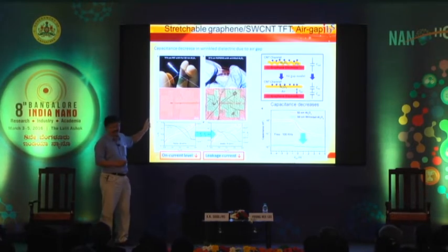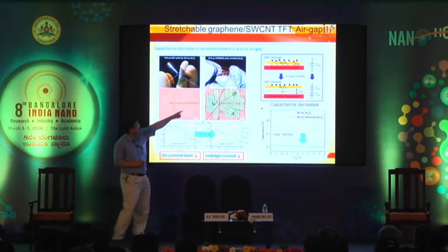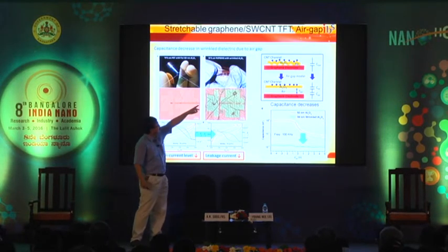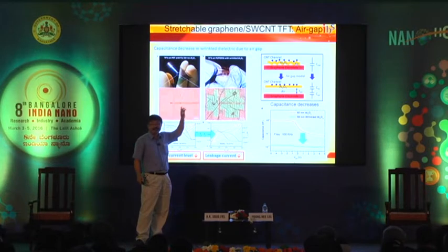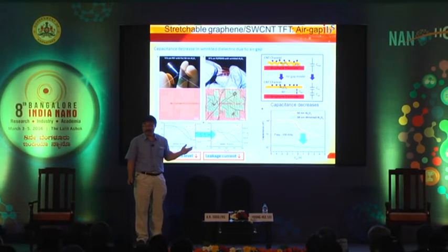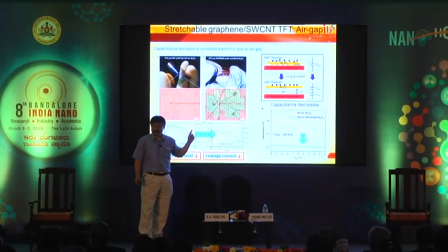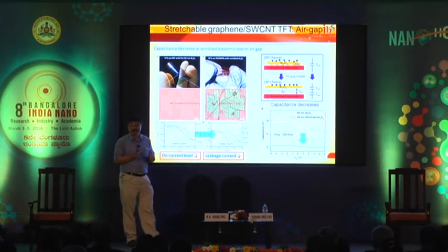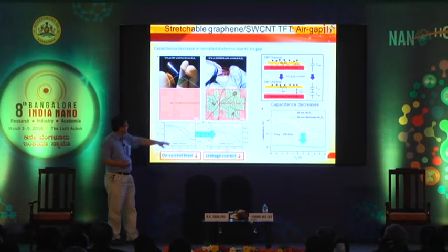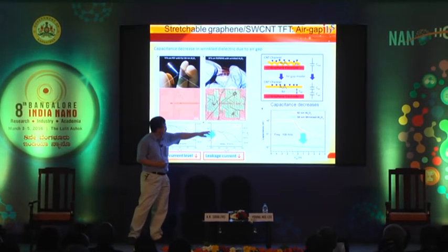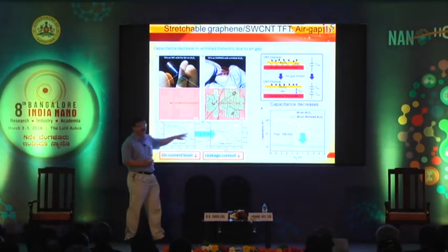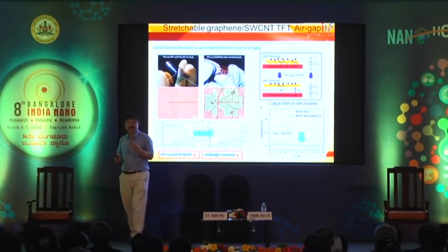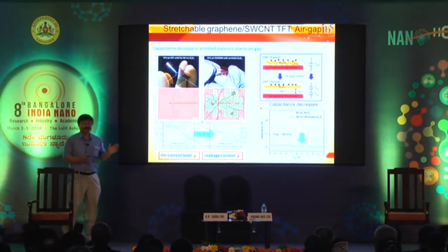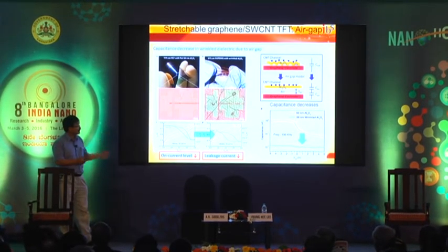And there is some delicate issue when you create this wrinkle structure, because if you look at the device, we have some kind of air gap. This is quite problematic. If you draw this equivalent circuit, we do have this air gap capacitance, which decreases the total capacitance. Actually, if you decrease the total capacitance of the device, the on current actually decreases. So there is some problem, but the advantage of this air gap is that, although the on current is slightly decreased here, this leakage current is completely prevented. So even better than the regular device. So this is an advantage.